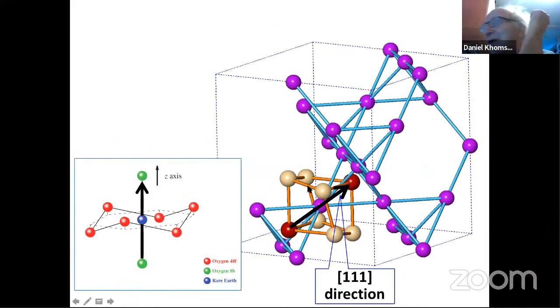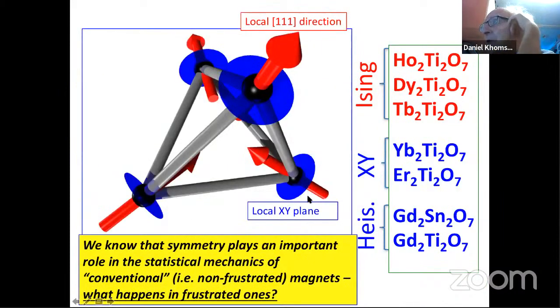Can I also ask a question once again? Yes. Dysprosium and holmium. Yes. One of them has an even number of electrons, another is odd. Yes. Is it true that then one should have a Kramers doublet and the other a non-Kramers doublet? Yes, that's a good question. Dysprosium is a Kramers ion, and J is 15/2. And holmium is a non-Kramers ion. It has J equals 8.